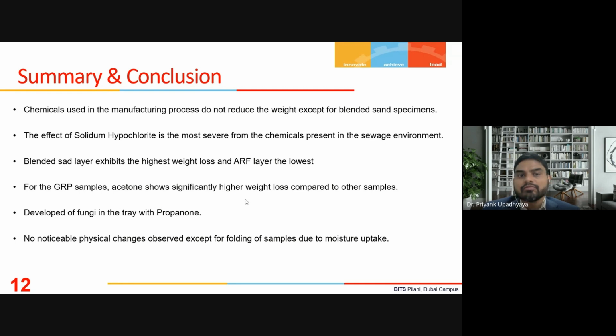In the case of the blended sand layer, we see the highest weight loss, and there are two reasons for that. One is that there is resin present in the system, which may be eaten away by acetone. The second is that it's a porous structure, so some of the sand particles and sand layers come off, and in some cases, we have noticed that the blended sand specimen breaks into two pieces. And for the GRP sandwich structure, acetone shows significantly higher weight loss compared to other samples. And as a substitute, because acetone is used for all the cleaning purposes while we are doing manufacturing.